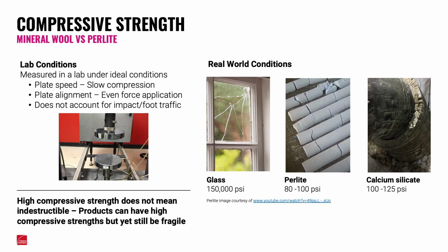And the advantage of testing in a lab is you can test at a slower plate speed, so that actually makes that load come in at a much slower rate, so you can actually get higher numbers when you do that versus having something move quickly. You have really good plate alignment, so that the force is evenly distributed, and it's kind of optimal from a test standpoint. But the one thing that doesn't take into account are things like impacts, like if you're walking on something or if you're tapping on it with something, it doesn't take that into account.